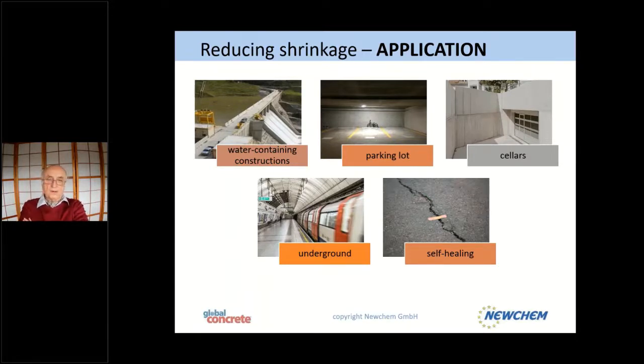In Japan, where most of the ettringite systems are used, they use it a lot underground, because the sandy soil would let the water through if the concrete would start to crack. With some trials we have, or literature we read, with magnesium oxide, you can do some concrete self-healing. And this is because if your concrete dries out and the magnesium oxide is not completely reacted, as soon as the crack is formed and water penetrates in it, the magnesium oxide will restart its reaction and form the magnesium hydroxide or other salts, and therefore the crack will be closed down. This is a pure chemical process.